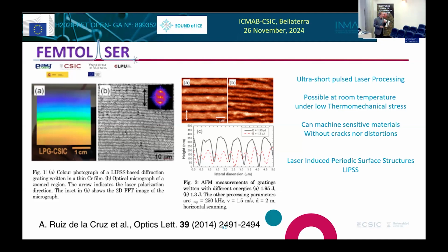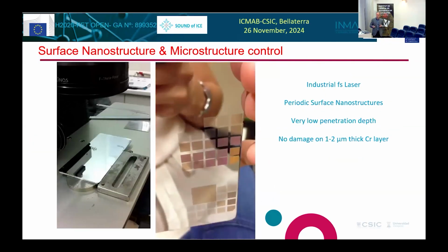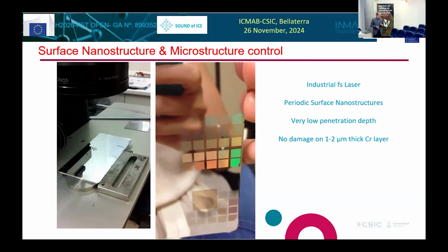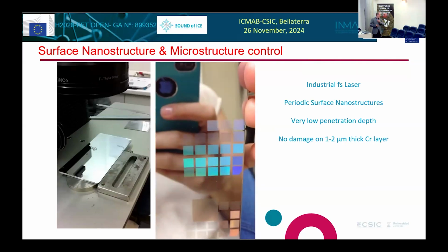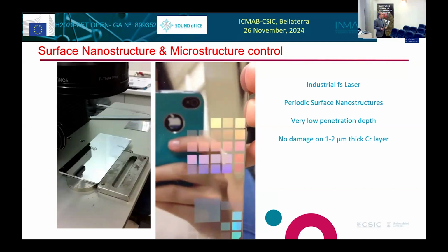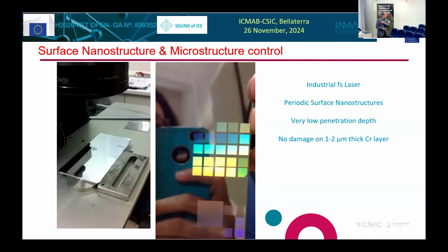So if you use a wavelength of about 1 micron, then you get about 900 nanometers is the periodicity you get. If you use one, like we use in 343 nanometers in the UV, you get the periodicity which is below 300. It's just above 200 nanometers. So you can really get very ordered nanostructures, which are periodic, very nice gratings, and you can do many things with them. For example, you can make diffraction gratings, which give you very pure colors, but they are dependent on the angle, as not before, you see? So this is a different phenomenon.